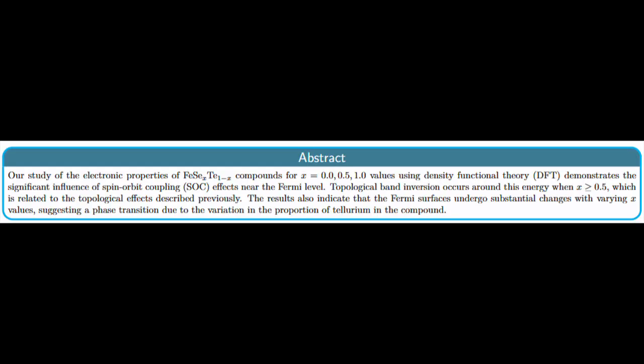Well, first a little resume of our work. Our study of the electronic properties of iron, selenium sub X, tellurium sub 1 minus X compounds for X equal to 0.0, 0.5, and 1.0 values using density functional theory demonstrates the significant influence of spin-orbit coupling effects near the Fermi level. Topological band inversion occurs around this energy when X greater or equal to 0.5, which is related to the topological effects described previously.